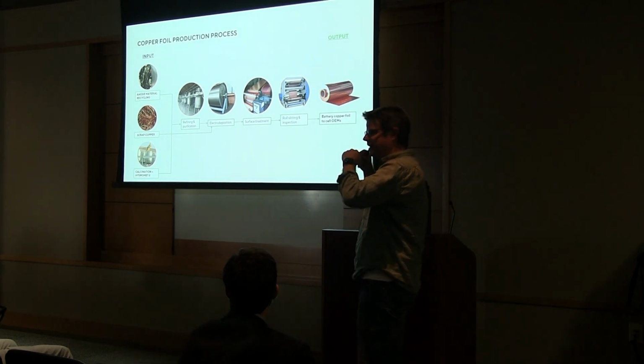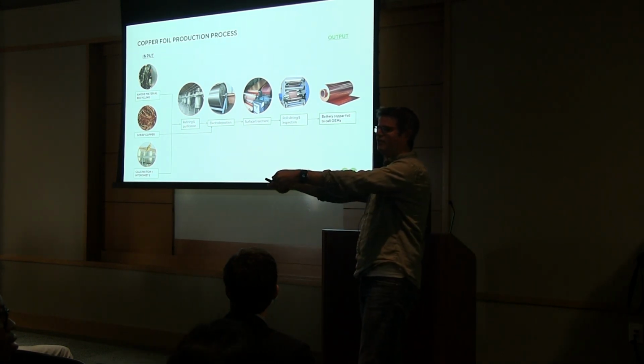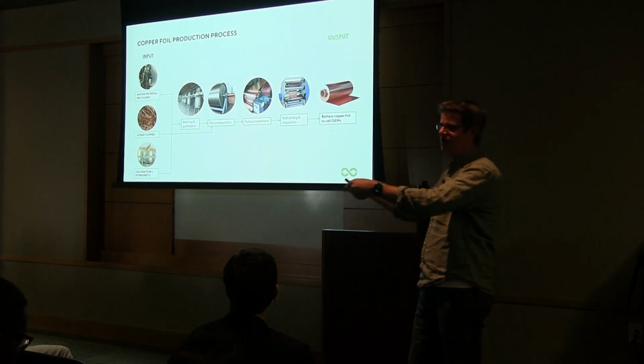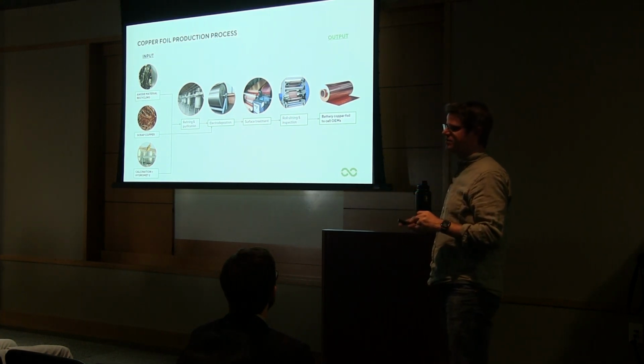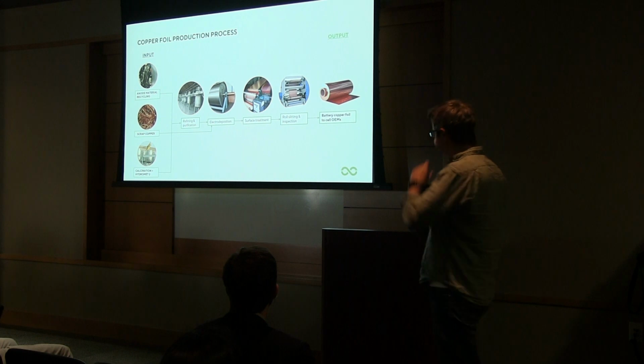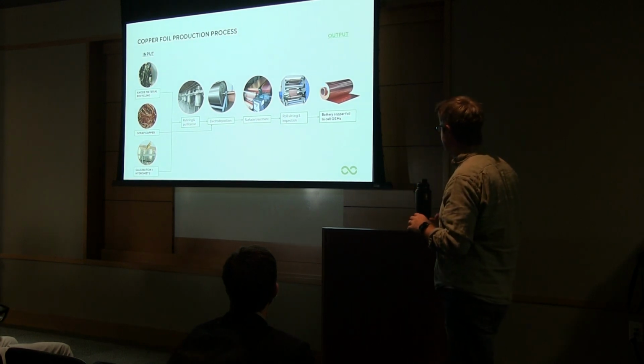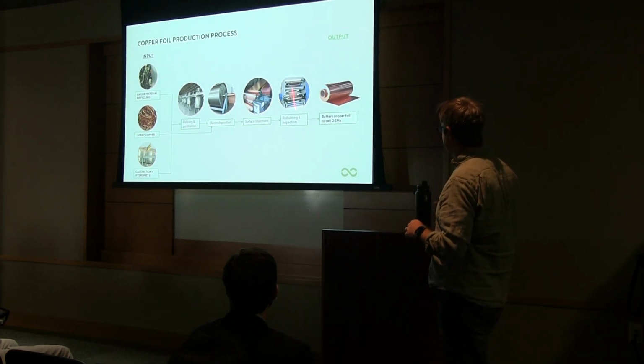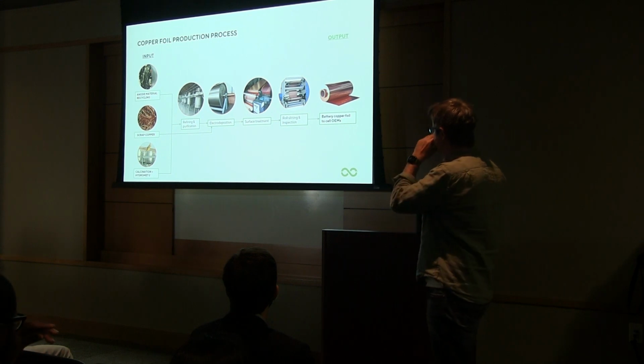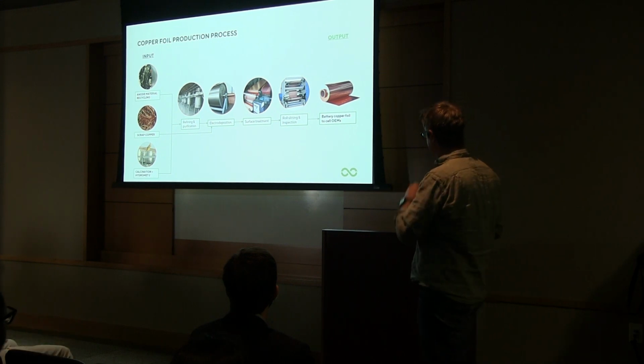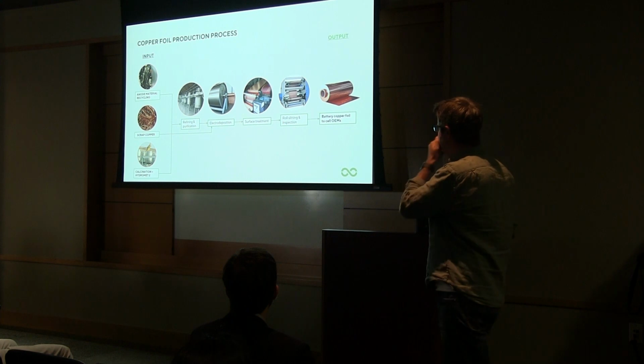Basically, this stuff rolls off the drum like a foil, like your aluminum foil at home. This stuff's 6 to 8 microns, so it's very, very thin. Battery grade foil. There's some surface treatment, rolling, slitting, and basically we get out of this battery grade copper foil.